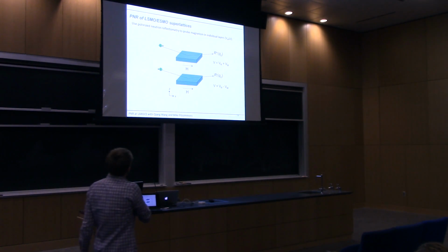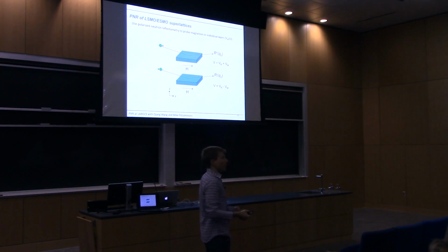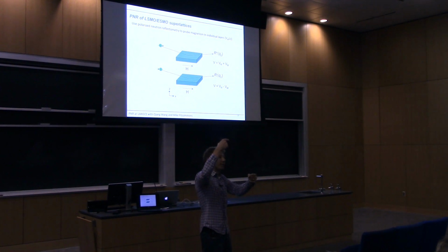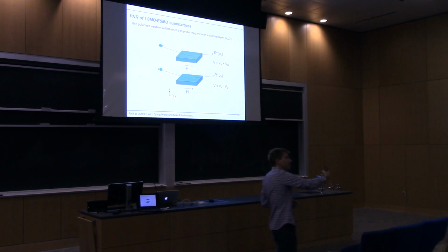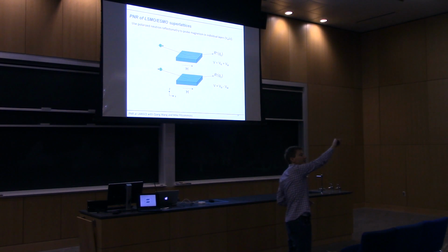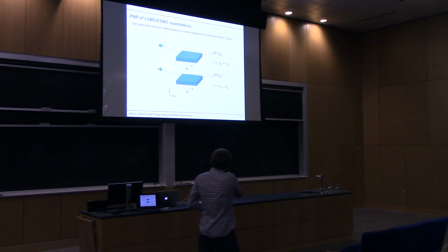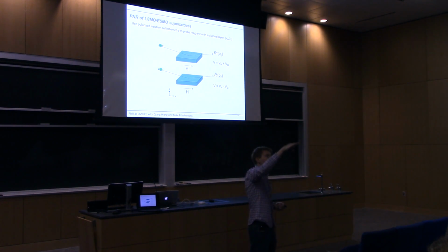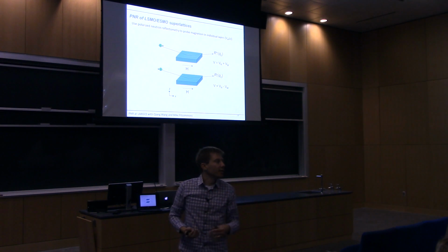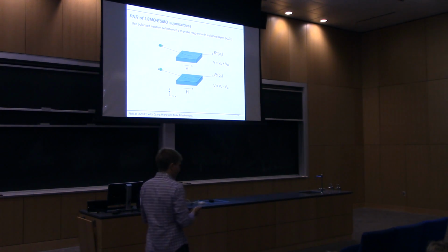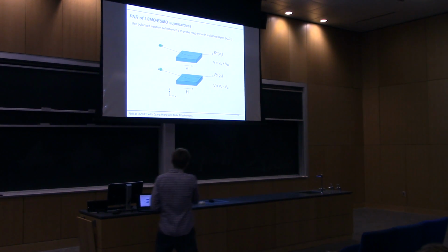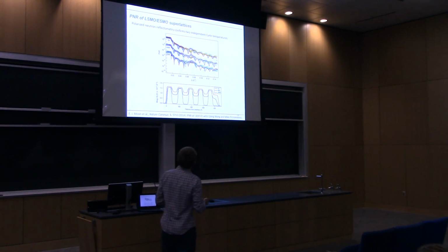We can actually prove it with polarized neutron reflectivity, where we come in with polarized neutrons that are aligned parallel to the magnetization in the sample and anti-parallel to the magnetization in the sample. And from that, we can get out the magnetic scattering potential. And this gives us a depth profile of where the magnetization is within the sample. So this is a commonly used technique for thin films and heterostructures of magnetic materials. And these were done with Mike Fitzsimmons, who's now at Oak Ridge.